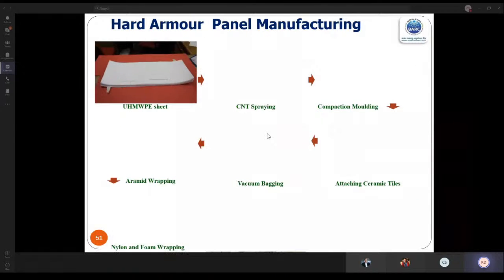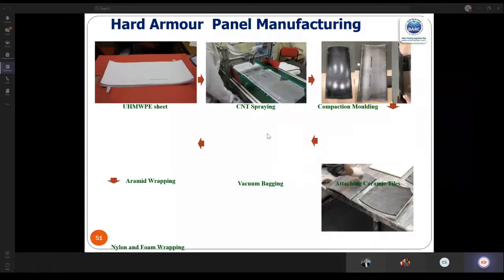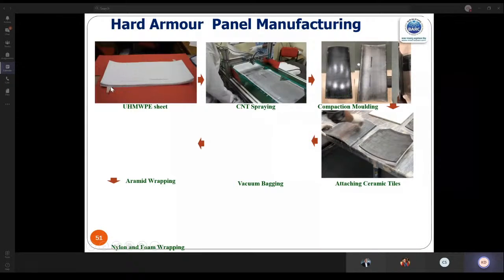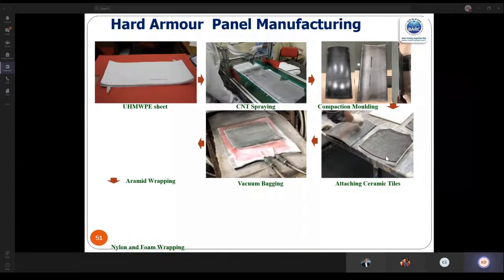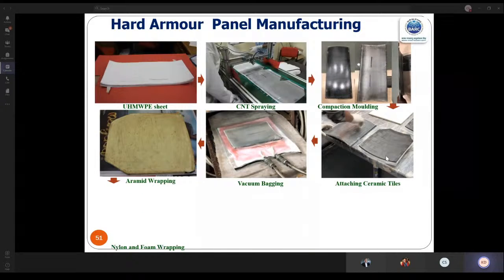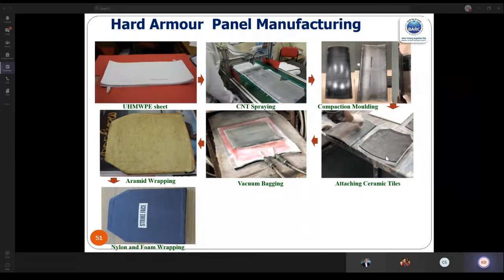I'll show how we typically do this. First, on an ultra high molecular polyethylene sheet, we spray carbon nanotube. We do compaction molding. Then the ceramic tiles are attached to that. Then comes vacuum bagging, then aramid wrapping, and then we end up with a hard armor panel.